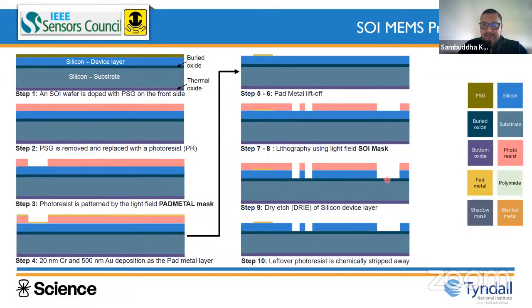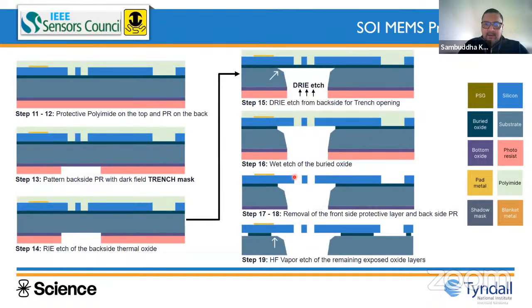This typically gives you a vertical sidewall profile. And here there are many design rules for designing this particular mask. Once the top silicon, or the device silicon, is etched, the next step is to remove the leftover photoresist. So we strip away the leftover photoresist, and then we go to the next process where we apply a protective front side layer, called polyimide, to protect the front side, because now the objective is to do processing from the back side to open the back side, and that's why we need to protect the front side. For that, we use a mask called the trench mask, and we flip the wafer and start processing from the back side.